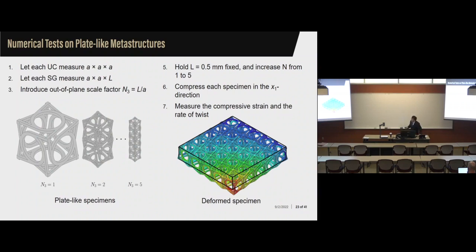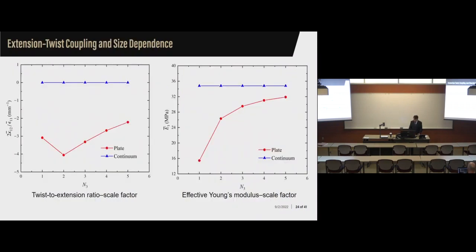But now what we deal with is, if you use our method, if n equals 1, you only have 1 unit cell, then what you want is the plate model, okay? Based on this 1 unit cell, you get a plate model, then there is an extension and twist coupling there. If you increase the number of unit cells through the thickness, basically they hold the size and the global dimension the same, but they reduce the length scale of the unit cell to try to find out the size effect. And we also did a prediction there. You found out that the two approaches, if you treat it as a continuum, you will not see any size effect. When you add more unit cells or you reduce the size of the unit cell, it does not change the properties you try to find out.